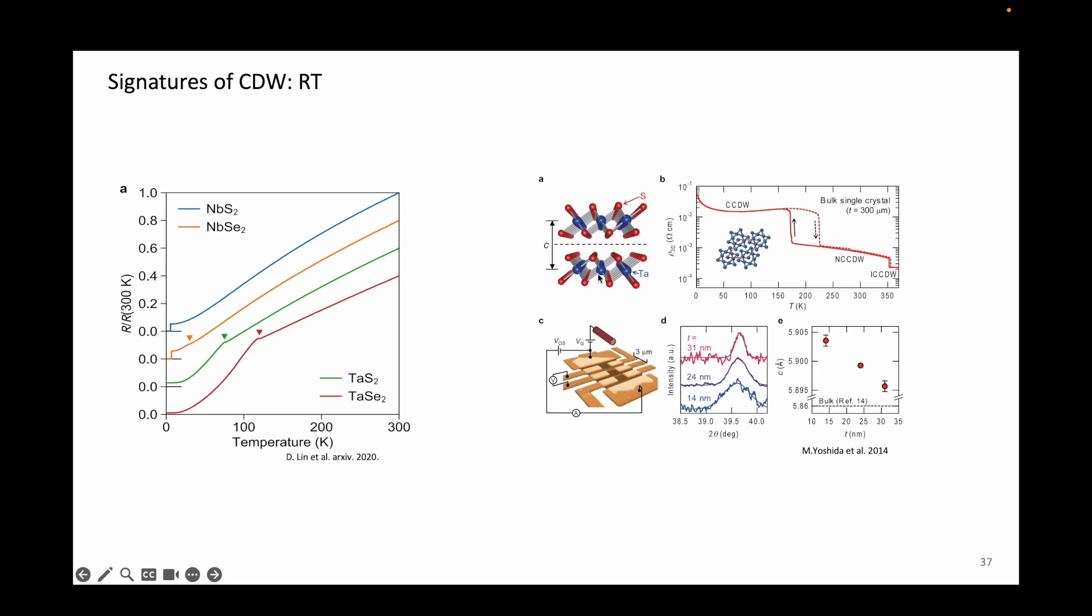On the right is again the 1T tantalum disulfide which shows a strong and sharp upturn in resistivity at the charge density wave transitions. They even show hysteresis in the temperature dependence.